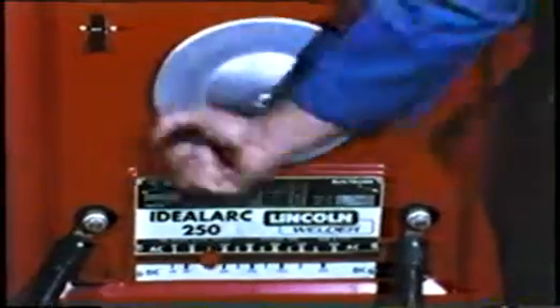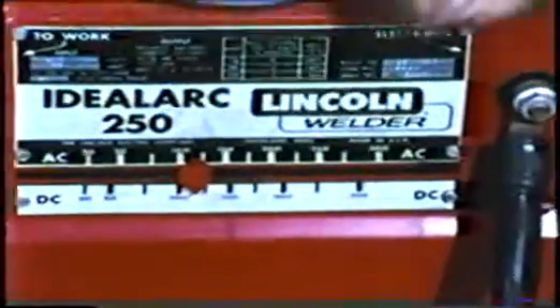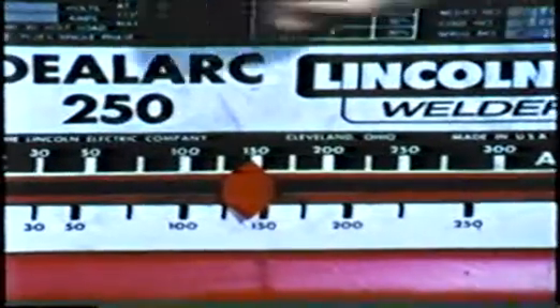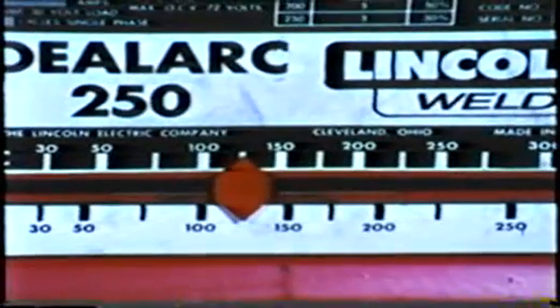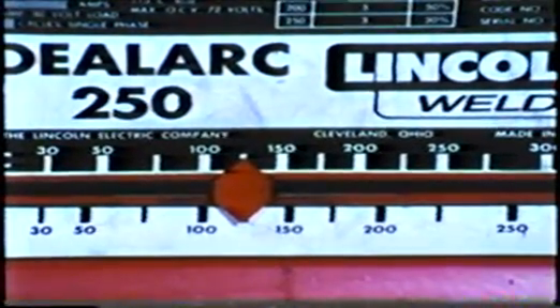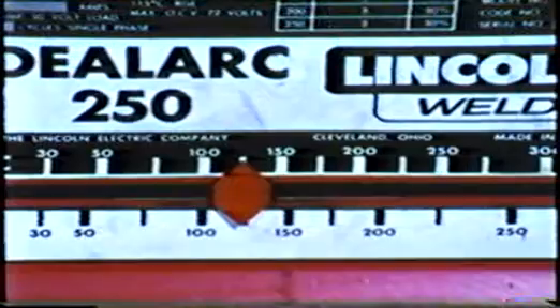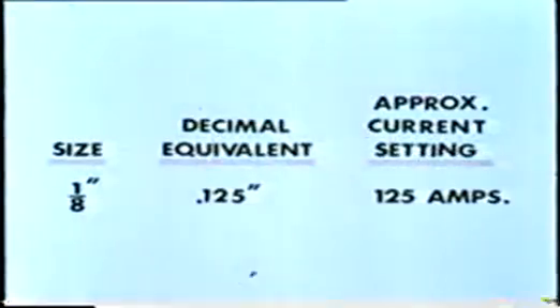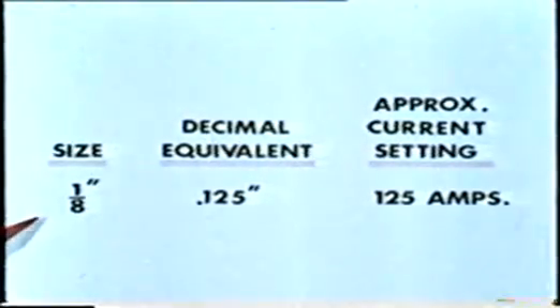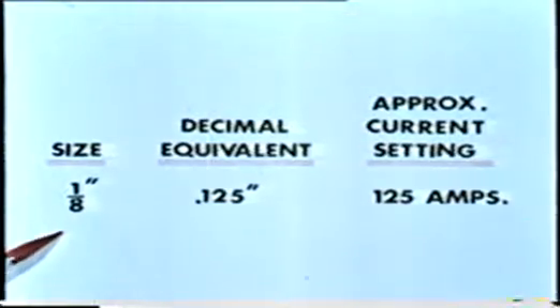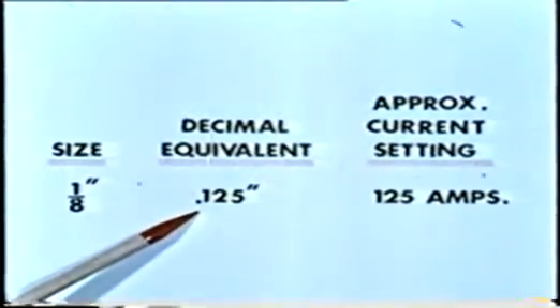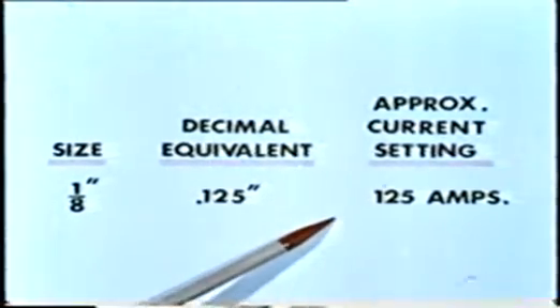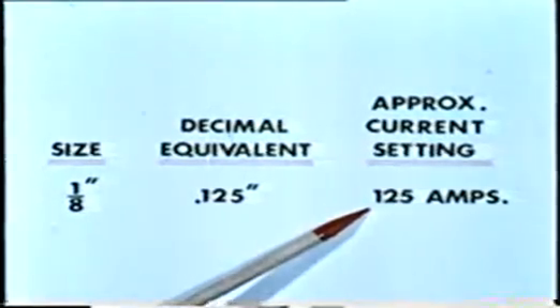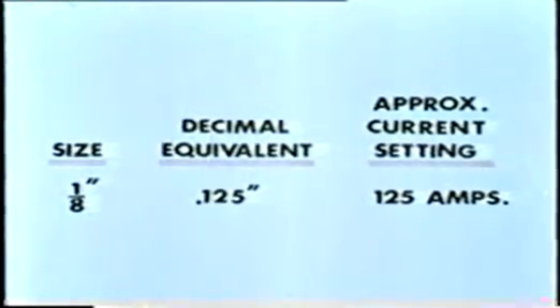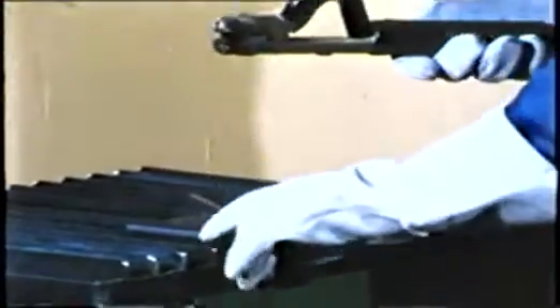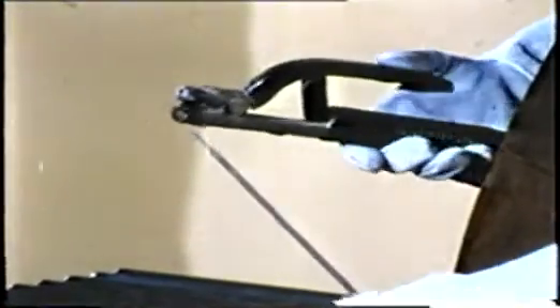The current should be regulated before welding. There are recommended current settings for all electrodes, but only through skill and practice will the welder learn the best current setting. An approximate current setting is equal to the decimal value of the electrode diameter. For example, if a 1/8 inch electrode is used, the decimal equivalent is 125 thousandths, and the current setting can be 125 amps. This is 1 amp for every thousandth of an inch. Insert the electrode into the electrode holder.